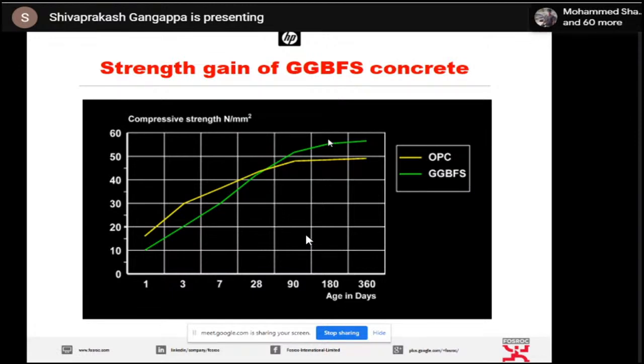But what is the amount of replacement we go for? In case of fly ash concrete, we went with 300 kg OPC and 100 kg fly ash. But in this particular case, the graph I'm showing is a 50% replacement. Means to say, out of 400 kg, 200 kg of OPC and 200 kg of GGBFS. So here, one point we got very clear is that the performance of the concrete in terms of durability will go better the moment you start using secondary cementitious material, because your strength gain will be much better in comparison with using only 100% OPC.